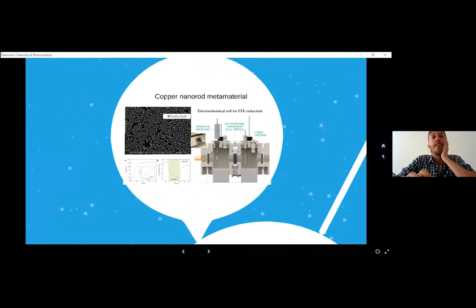Towards the end, one of the most prominent applications would be copper nanorod metamaterials. Copper is probably the only really nice plasmonic material in the visible regime, but also from the catalytic point of view, it's a really well-known catalyst for CO2 reduction and the generation of C2 products, right? So C-C coupling reactions. Copper is a really interesting material for us because it has both plasmonic properties and really nice catalytic properties towards CO2 reduction.